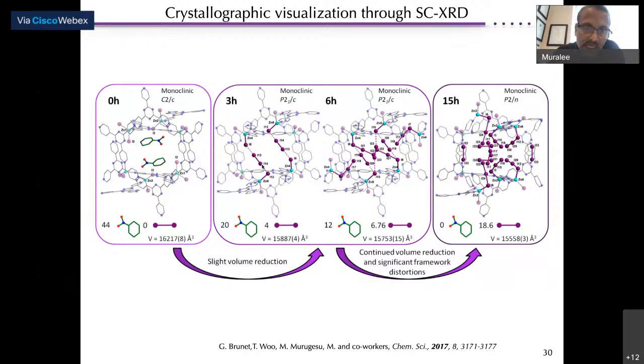on one of the zinc atoms. And you can see another one. This provides a really nice anchor for these I2 molecules to come and clip on and form an I4 type motif. You can see here. And one interesting feature is you're going from a much larger volume to a smaller volume in this case, and of course the space group changes. That's because these iodines are bringing these pores within them and collapsing in a way, not collapsing the whole framework, but just bringing these closer, so the unit cell is becoming smaller.